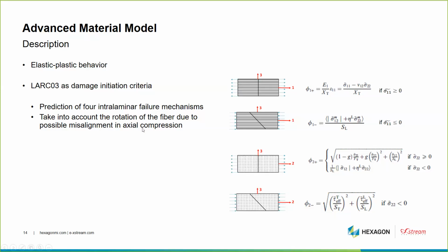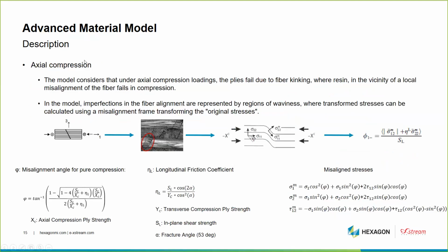So if we look at that in detail, when we are in axial compression, the model will consider that under axial compression loading, the ply will fail due to fiber kinking, where the resin in the vicinity of the local misalignment of the fiber will fail in compression. So this is what is represented here on that scan: we have a misalignment that appears, and in the vicinity of this misalignment, the matrix will fail in compression.